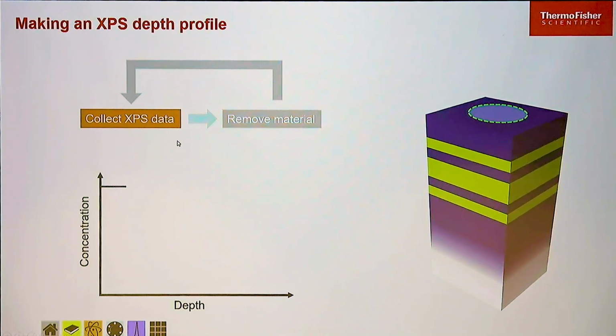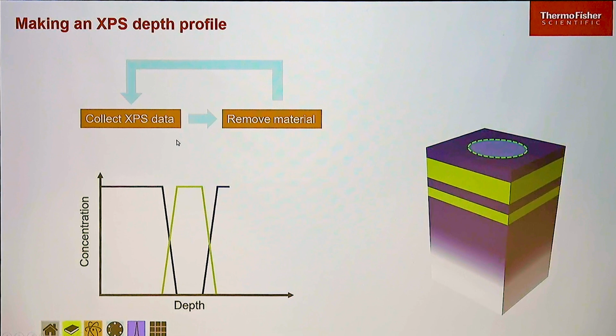And we just keep cycling, and as we do that, we quantify the amount of material we have, and that generates us a profile. This is a little bit tricky to convert into depth. Usually we'll have to quantify against a standard material and just say, okay, this is the etch rate we would have had on silicon oxide or tantalum pentoxide or some other material that we can easily grow a known oxide thickness on. It's very rare you can actually get good standards of the materials you're etching.